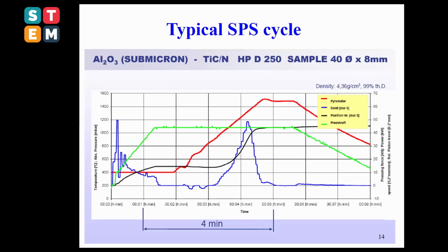Basically, here you have the typical thermal cycle that you can apply. The red color is the thermal profile. The green one is the pressure applied, but the important curve here is the black one. This is the shrinkage curve for the densification, where you can clearly observe here after 4 minutes, you attain the plateau. That means the sample, the submicron alumina oxide, is fully dense.